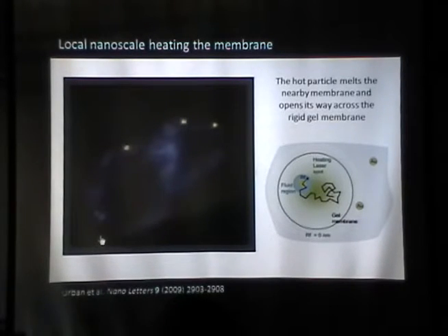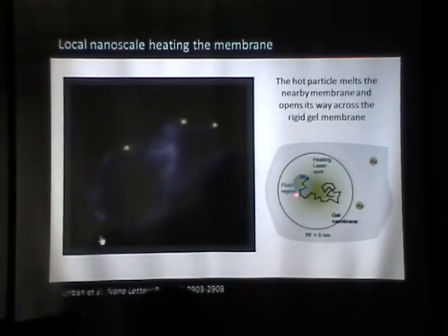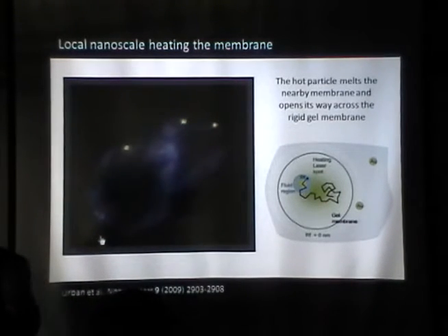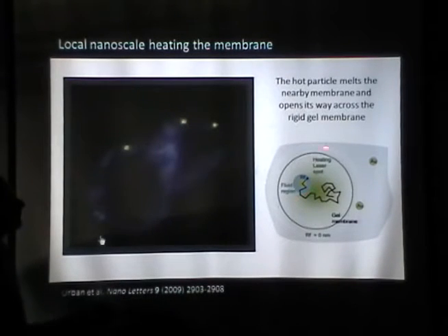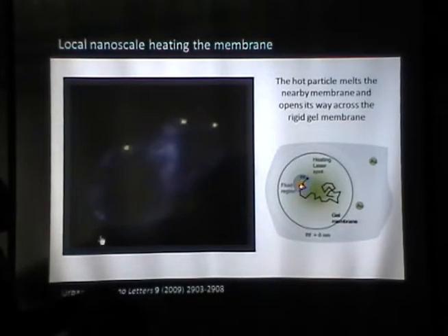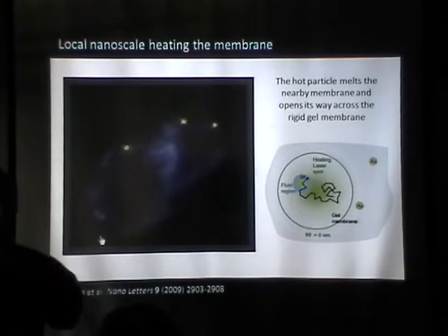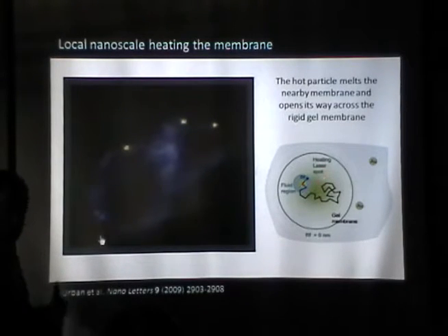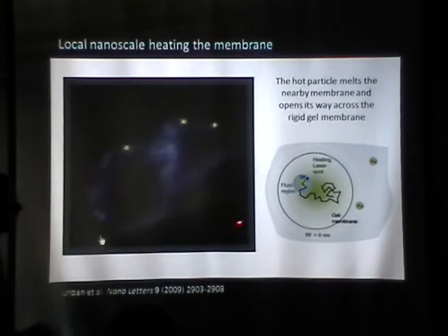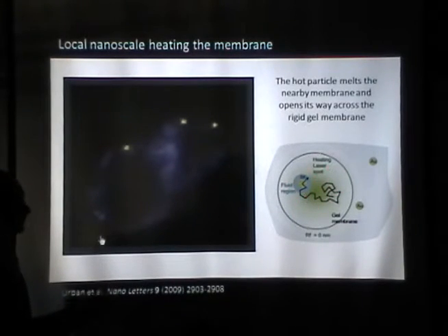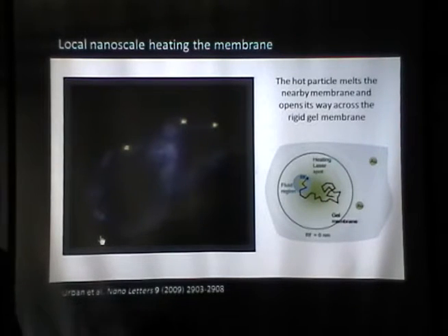So what's happening is that we have the gold nanoparticles fixed on the gel phase membrane because they interact strongly with the phospholipids. So now we have our heating laser spot, and if a nanoparticle is inside of it, it absorbs light, it heats up, and it can melt a small region around it. When it melts, now it can move together with the lipids, and as it moves, it melts a new region, and so on. So basically the nanoparticle could move as much as it wants inside the heating laser spot, while the other 2 remain fixed.